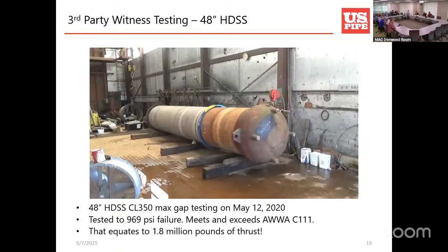And then we had to go through a whole testing process. We can't just claim that we meet AWWA. We have to go through a third-party test, regular testing, and then third-party testing. So this was actually a 48-inch HDSS Class 350 test that we did back in 2020. And it actually tested to 969 PSI to failure, which meets and exceeds the standard. And that equates to about 1.8 million pounds of thrust force. And there is a video there if you want to play that.